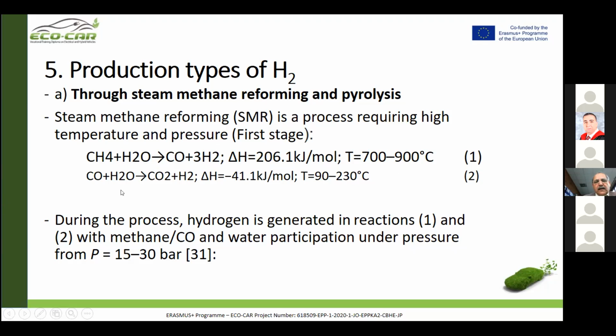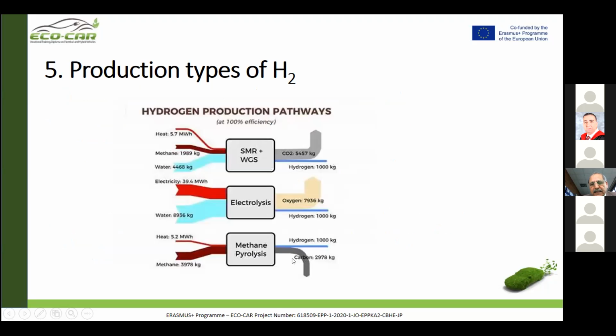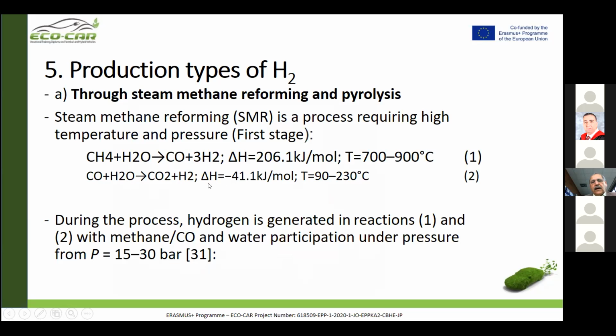In the second stage, the carbon monoxide can react with water again to produce CO2 and hydrogen again. And in this case, we release energy, heat, with a specific heat of about 41 kilojoule per mole, and the temperature is about 90 to 230. In the other possibility, we have methane and heat, then we have hydrogen and carbon. That is what we have at the end.